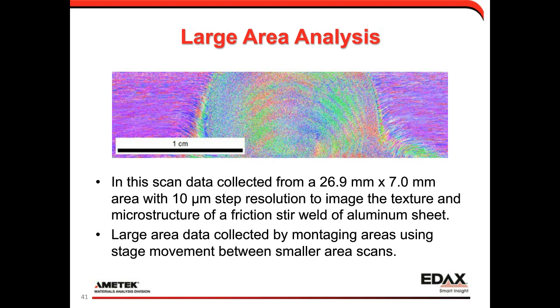In this case, this is EBSD data collected from a 27 millimeter by 7 millimeter area with a 10 micron step size spatial resolution to image the texture, the orientation and the microstructure of this friction stir weld. So you can see the base material on the left and right-hand side, and then we see the weld nugget there in the middle. It has this onion ring type of pattern of different layers of grains. But we can get a large area view of the microstructure.